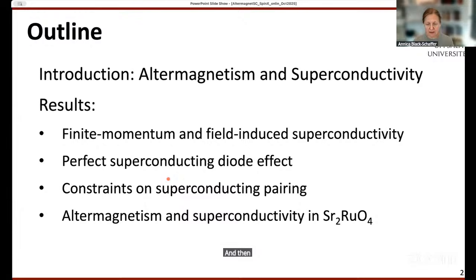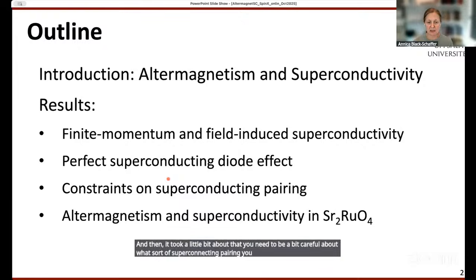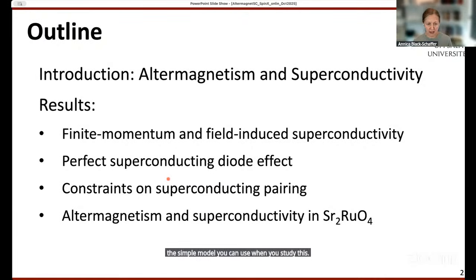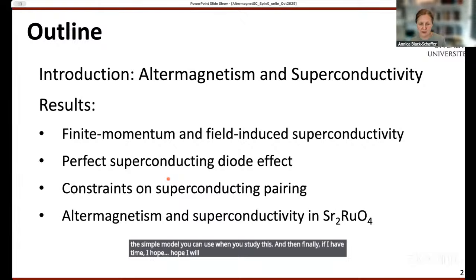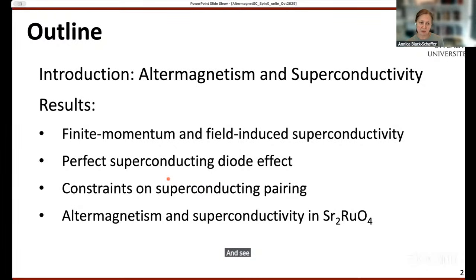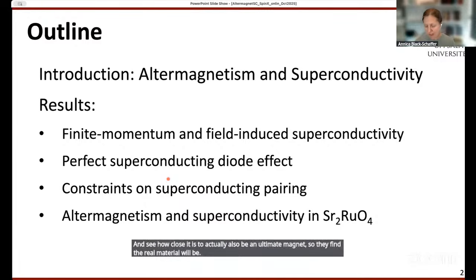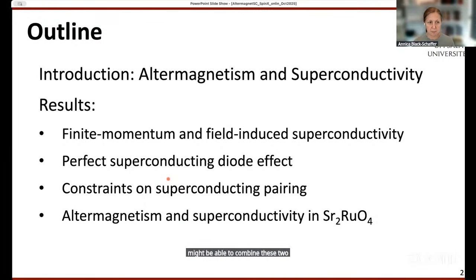And then talk a little bit about that you need to be a bit careful about what sort of superconducting pairing you consider in altermagnets, because it does have, as you may know, the sublattice structure, and that actually limits the simple model you can use when you study this. And then finally, if I have time, I hope I will, I'll talk about some results we have, and we did some ab initio modeling on strontium ruthenate, which is an intrinsic superconductor, and see how close it is to actually also be an altermagnet. So there I find the real material where we might be able to combine these two effects.